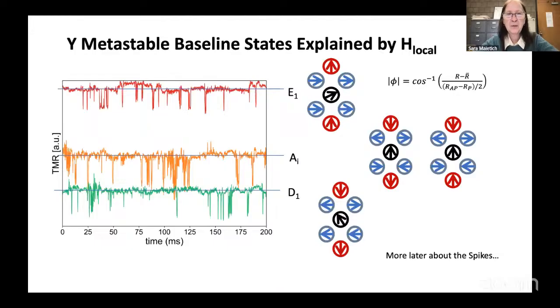I should also point out that we can associate the measured resistance for the baseline with these different levels with local spin configurations, some of which have no canting, some of which have canting away from the fringe field, towards the fringe field. So this is one of the long-lived states that has a very slow relaxation time. These have short relaxation times of a few nanoseconds. So this helps to give you memory.